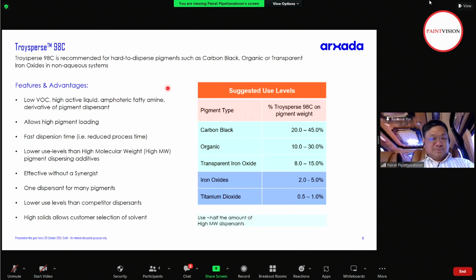Let's talk about these products in a little more detail, including performance evaluation. 98C, as I said before, is a fatty amine derivative. So it's good for hard to disperse pigments, such as high surface area carbon black. For example, Lamp Black 5000 from Birla, FW200 from Orion today, and you have Monarch 1300, 1400 from Cabot. So these are really hard to disperse carbon blacks that have really high surface area, really fine particle size, high jetness type. Also organic pigments, for example, phthalo blue, phthalo green, and violet. Even transparent iron oxide pigment for non-aqueous system.